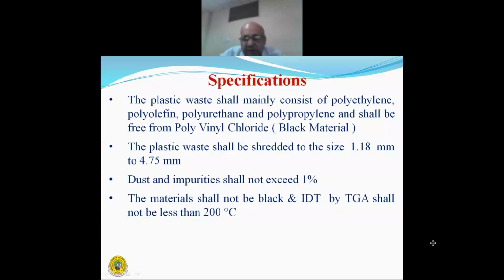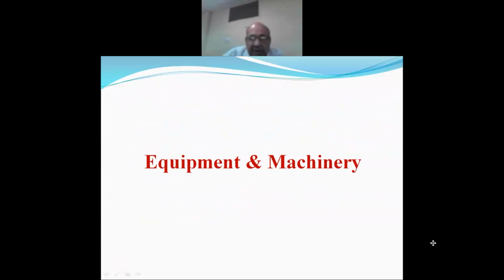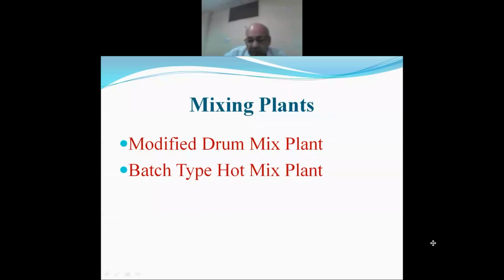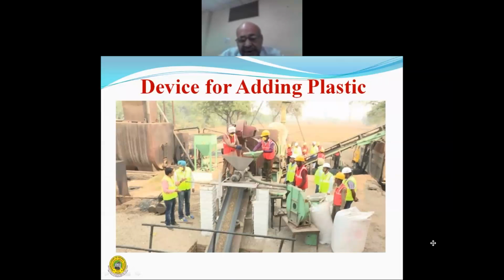One lane kilometer of the road requires 370 kg of plastic waste for open graded premix carpet. One lane kilometer means 3,750 square meters. 370 kg of plastic waste for open graded premix carpet, 720 kg plastic waste for closely graded premix carpet, that is also called mixed seal surfacing, and 750 kg plastic waste for BC. A load of plastic waste may comprise 1 ton, which should be tested for field level tests, and the recommended field level tests are sieve analysis test and ash content test.